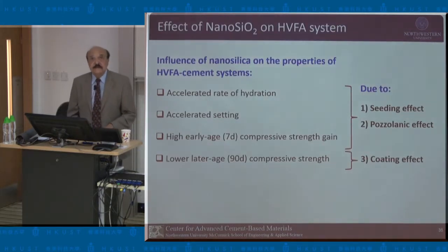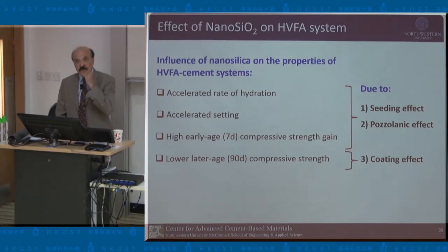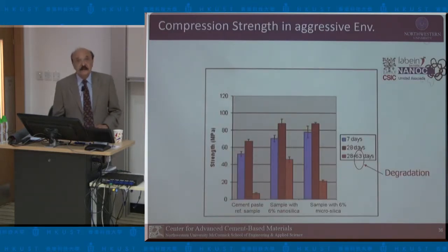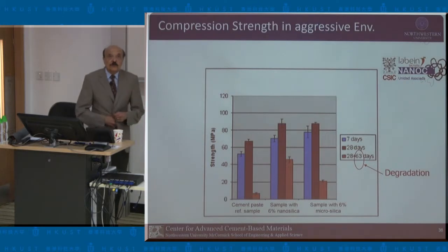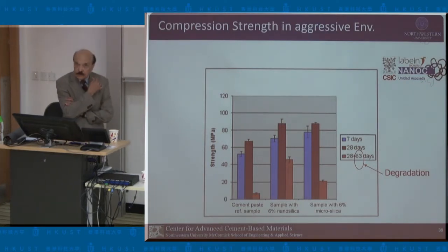So with nanosilica, they have identified three effects as far as the hydration kinetics: the seeding effect, the pozzolanic effect that we already know, and then of course this coating effect has to be included when you are analyzing the effect of nanosilica. Now, nanosilica of course also influences long-term properties. And this is the work that I'm presenting.